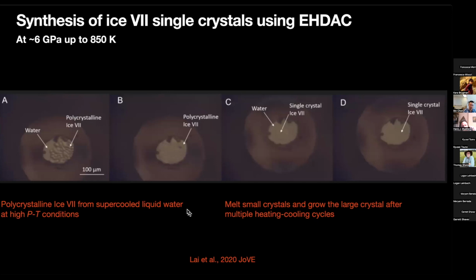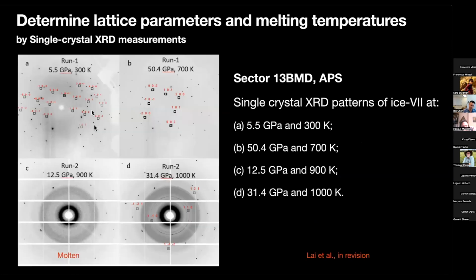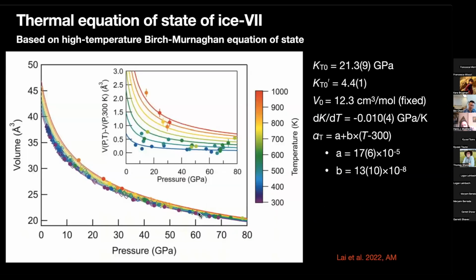By using the externally heated diamond cell, we could synthesize a very nice single crystal of ice VII. So those are the single crystal data of ice VII at high PT conditions. And this sample is molten, as we can see. From the data, we determined the thermal equation of state of high pressure ices to around 80 GPa. This work has been published in American Mineralogist.